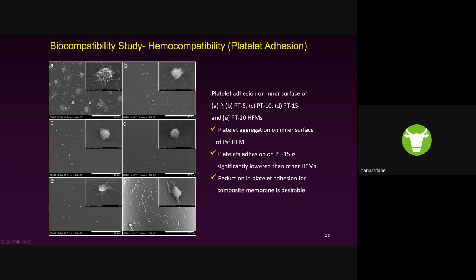You can also see these platelets showing some tentacles. They deform. These are deformed platelets, but this deformation is not that significant. In an ideal situation, there should not be any platelet adhesion or deformation on any foreign surface. But this is quite significantly reduced with the composite membrane that we prepared.